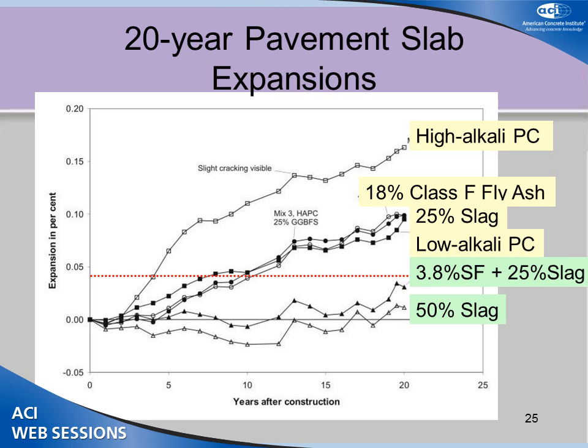Again, the maximum expansion is in the order of 0.15, which is intermediate between the unreinforced beams and the reinforced beams in terms of total expansion. And again, it's the same order. Here, the low-alkali cement and the slag, the 25 slag and the 18 ash didn't control the cracking. The two that have controlled the cracking over the 20 years are the ternary blend and the 50% slag. So it's consistent in all the field exposure, and it's consistent with the concrete prism data, and it's consistent with the 14-day mortar bar test.